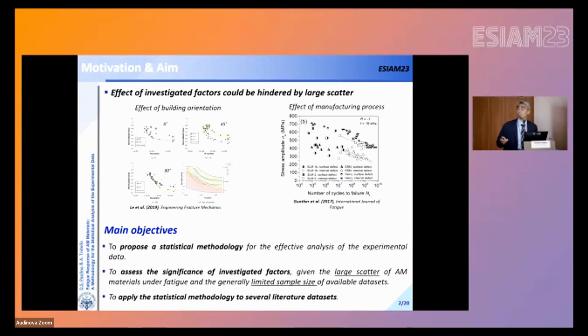The first picture on the left is taken from the AM literature, and is related to the fatigue response of AM materials built with different building angles: 0, 45 degrees, and 90 degrees; 0 horizontal, 90 vertical, and 45 in between. And the last picture in this set of SN plots reports all the data together. And as you can see, the scatter bands are quite large and cannot permit a clear assessment of the effect of the building angles.